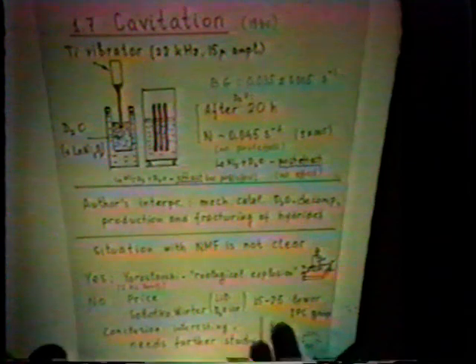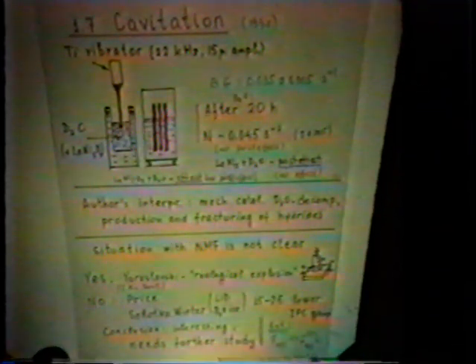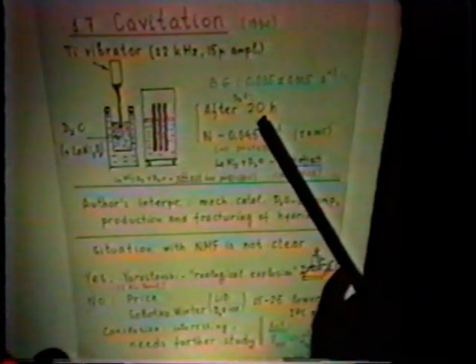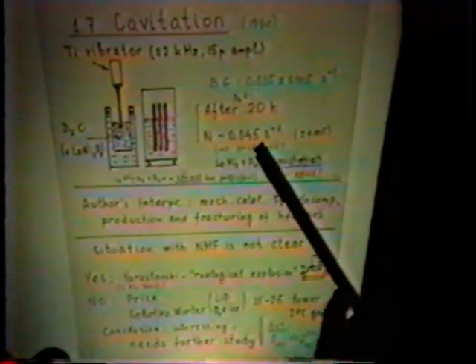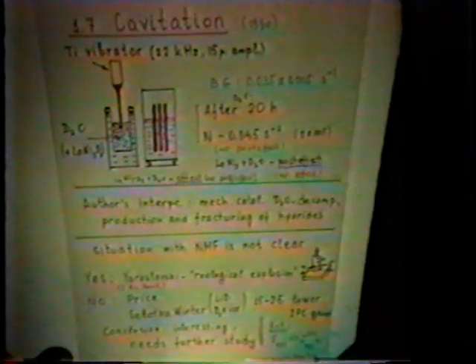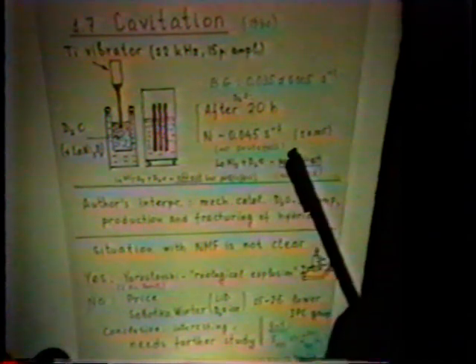The last experiment of this group is neutron measurements during cavitation. A titanium vibrator was immersed in heavy water, and after about 20 hours of running, they observed some excess of neutron emission above the background level. After vibration was stopped, there was no post effect in this case. When they processed this material a little bit, they observed practically the same. There was an effect and there was no post effect.